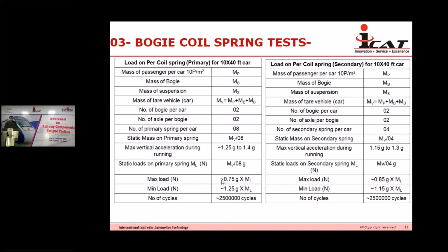Then maximum load is 0.75 G to ML. ML is basically the static load. And then minimum load is 1.25 G into ML. So these are the maximum and minimum loads we need to derive, or this is provided by the customer based on their calculations. It is not a thumb rule like 0.75 G or 1.25 G. It is basically the data they collected from the railway or already derived data. So the number of cycles is, as I said, 25 lakh cycles. We need to run the test between these two values, or it can be on the higher side, like some FOS or something they have considered.